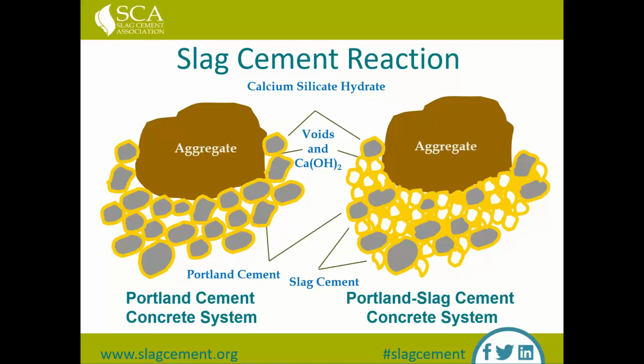On the right, looking at the Portland slag cement concrete system, you'll notice there's fewer hydrated cement particles, fewer voids, and more of the CSH present. There are a couple different benefits you're getting from the slag in this situation - one is physical and the other is chemical.